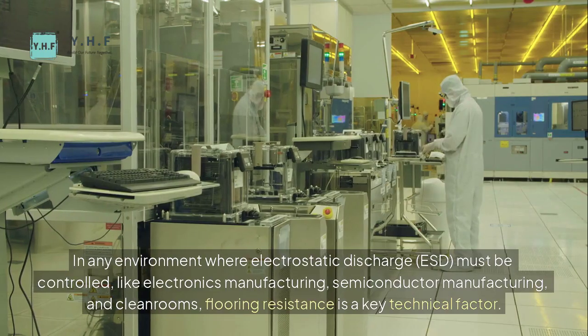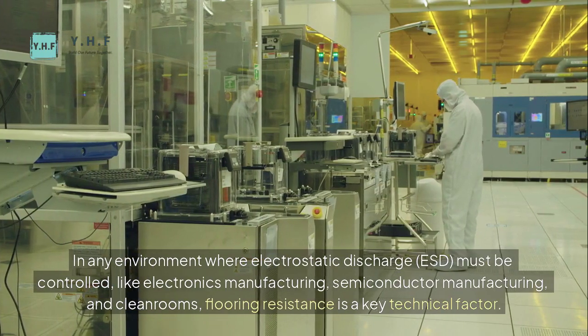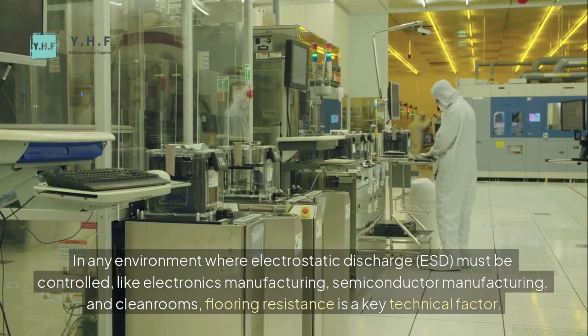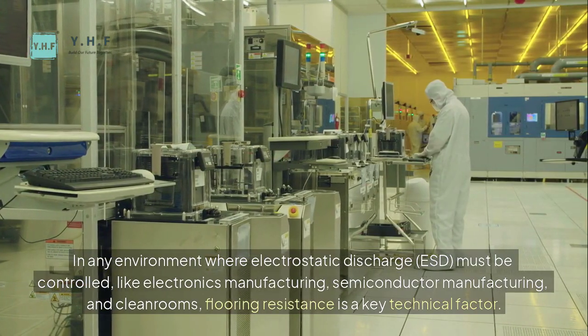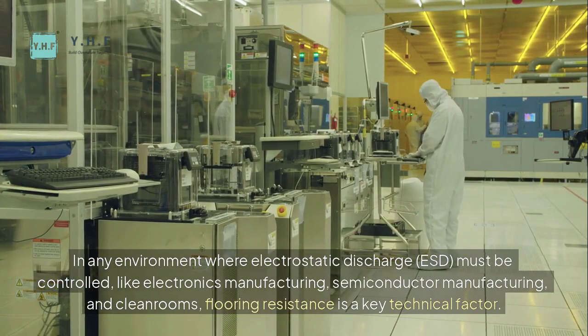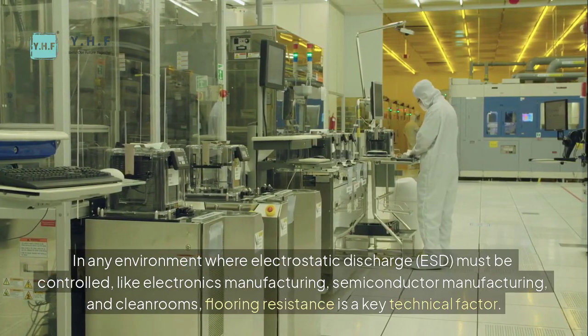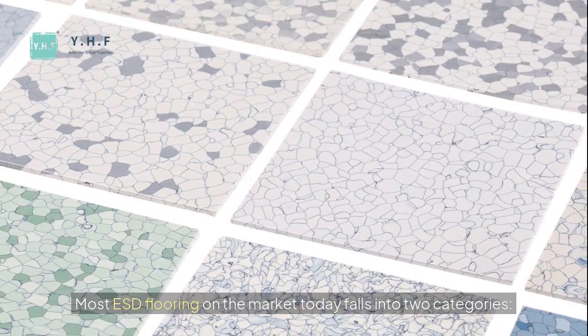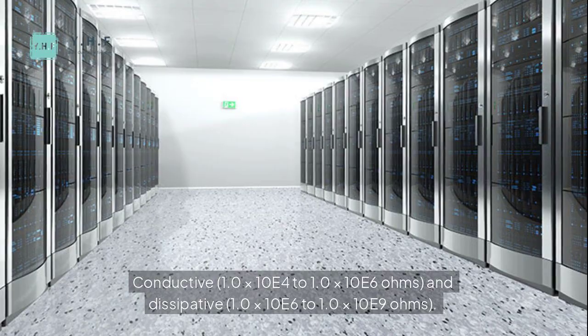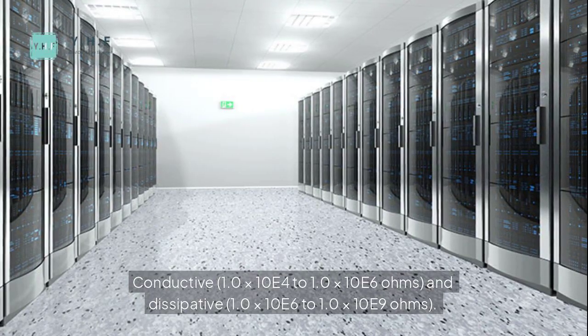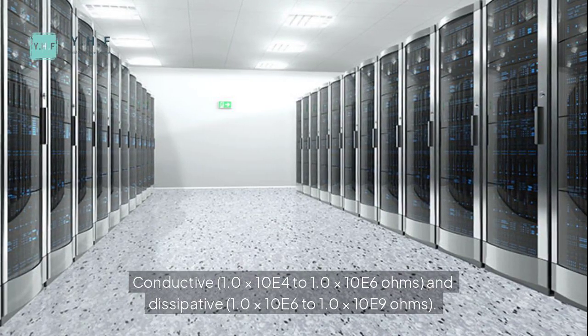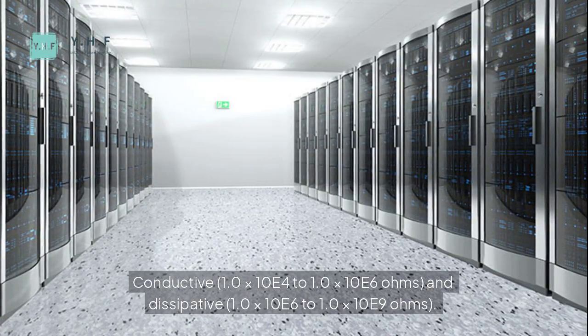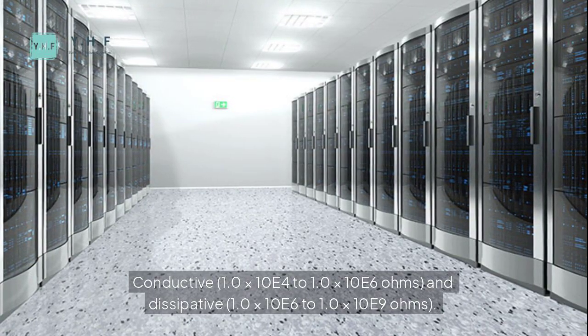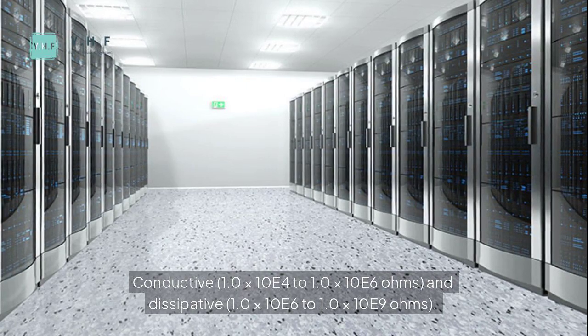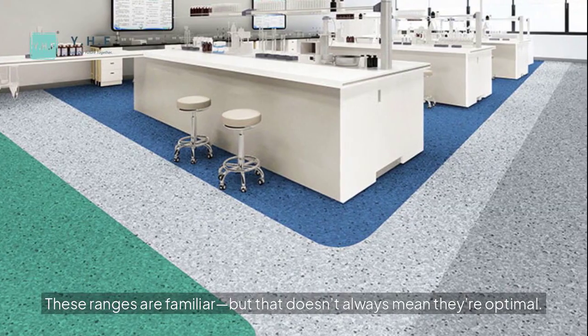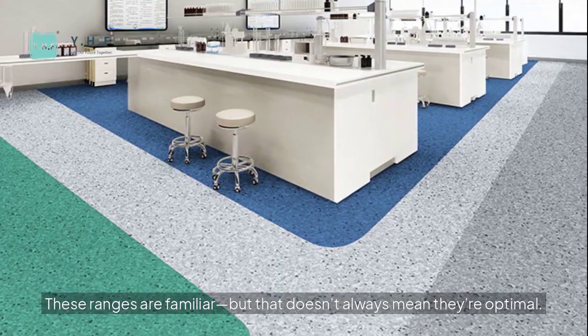In any environment where electrostatic discharge, ESD, must be controlled, like electronics manufacturing, semiconductor manufacturing, and cleanrooms, flooring resistance is a key technical factor. Most ESD flooring on the market today falls into two categories: conductive, 1.0 × 10^4 to 1.0 × 10^6 ohms, and dissipative, 1.0 × 10^6 to 1.0 × 10^9 ohms. These ranges are familiar, but that doesn't always mean they're optimal.